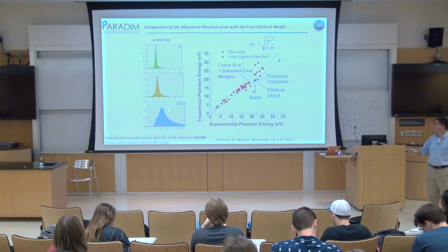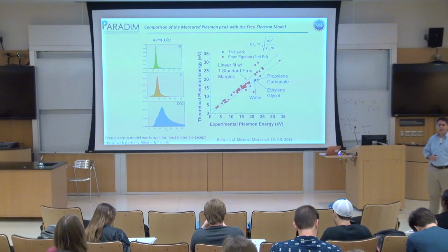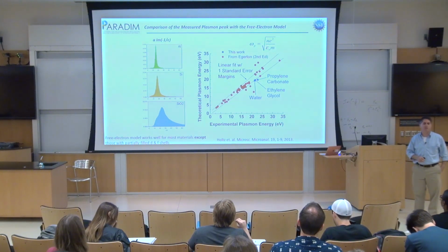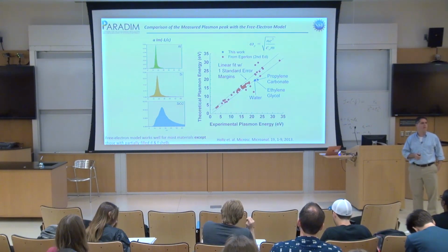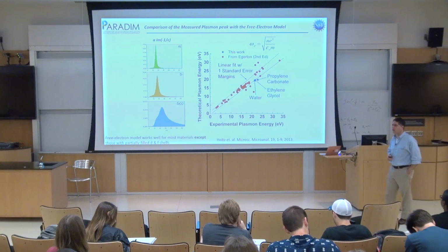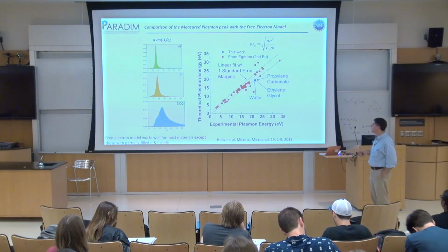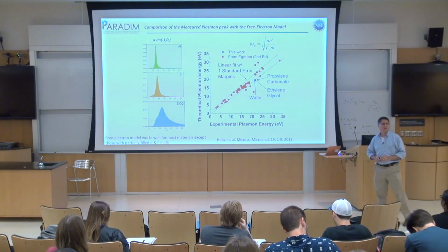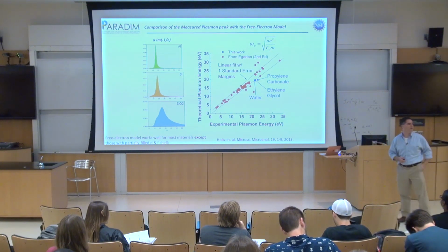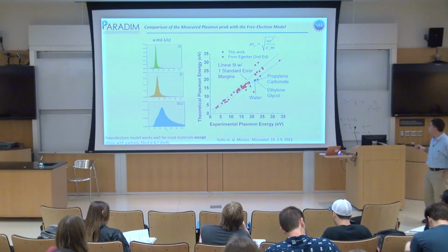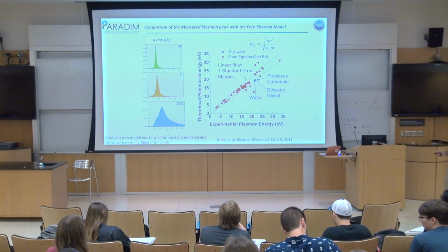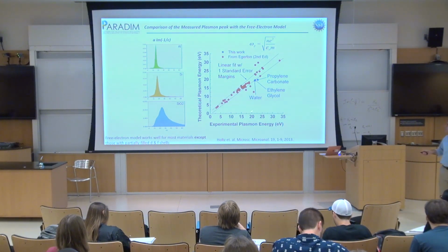This is the biggest scattering you get on the atom anyhow. And so basically, if you know the plasma frequency, you can actually make a guess at the inelastic mean free path. So the formulas used in the Gatan code assume a free electron gas when they magically tell you how thick the sample is. They're telling you how thick the sample is, assuming there are no atoms in there. It all got smeared out.